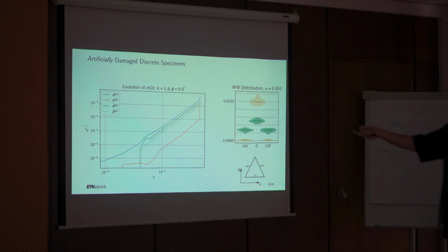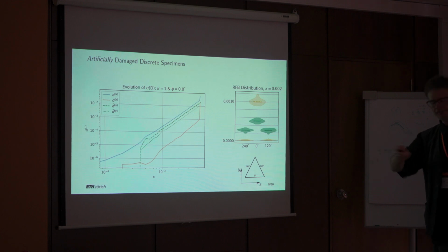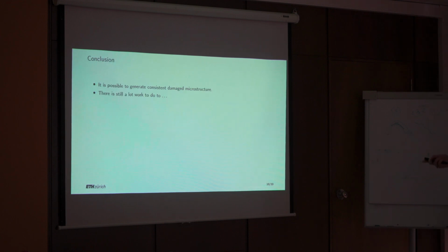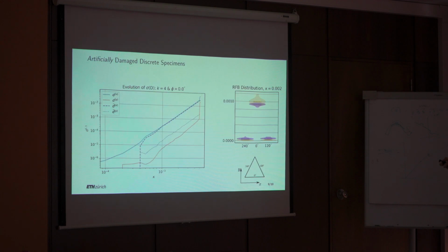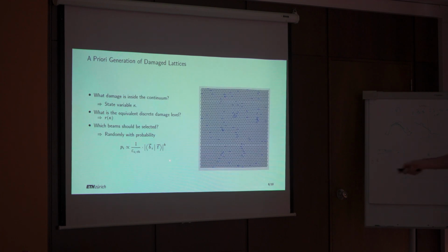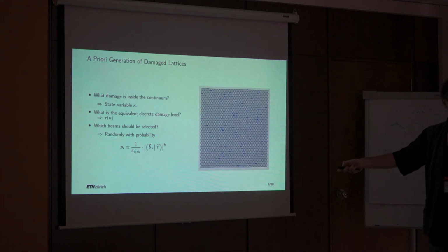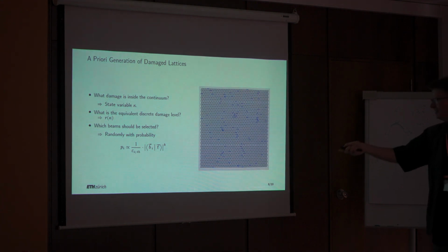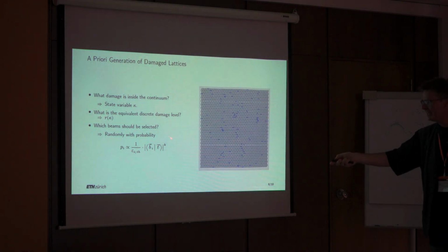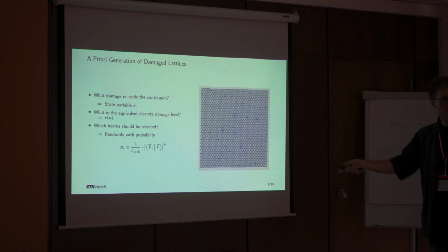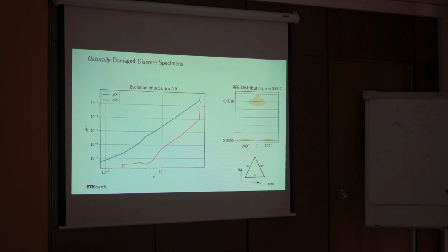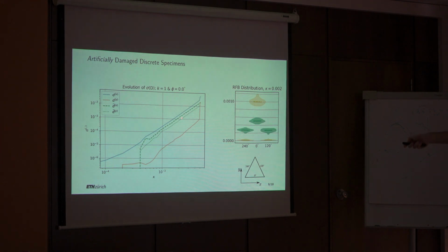And now we go to k equals 1. This is basically everything weighted. Oh, excuse me, I forgot this. Here you have this exponent k. I call it damage weight, and it is basically to make this factor more important, to give it more weight. And here is k equals 1, and here you see that the damage in x direction is too low, while the damage in y direction is far too high.